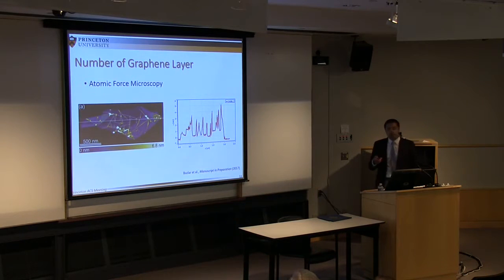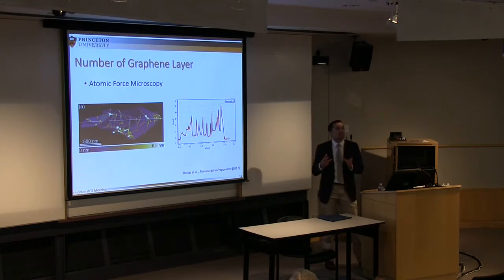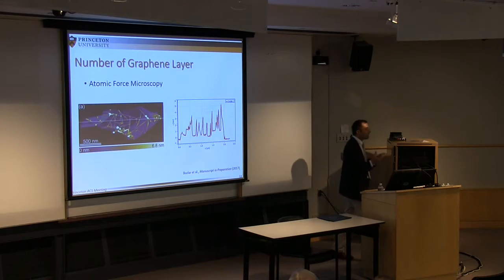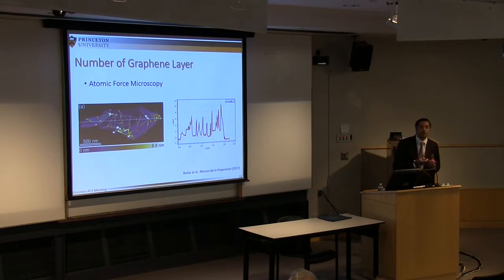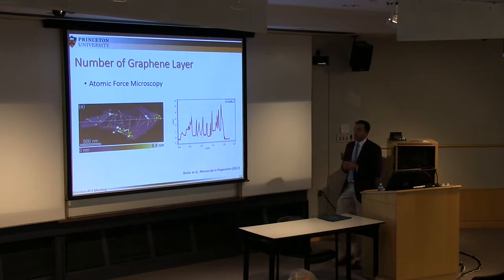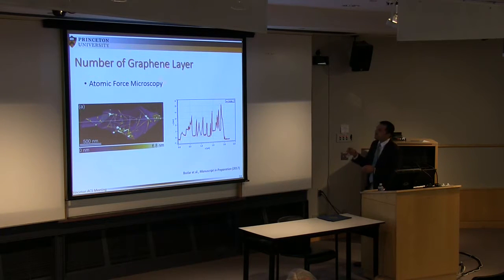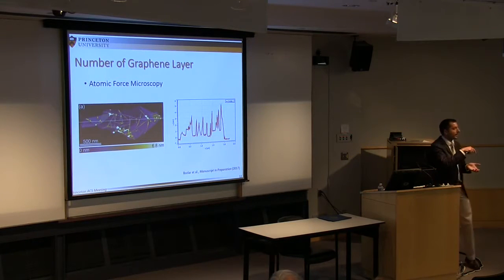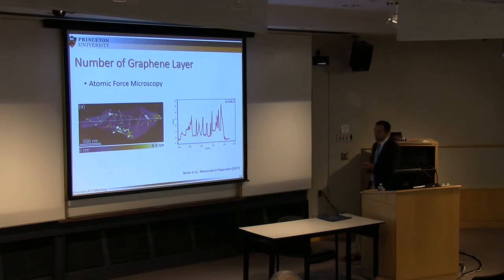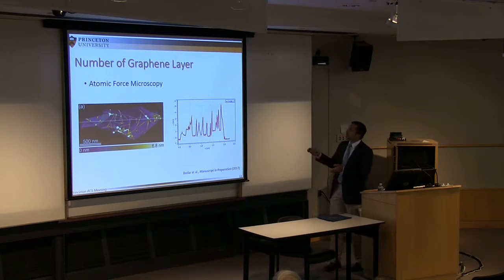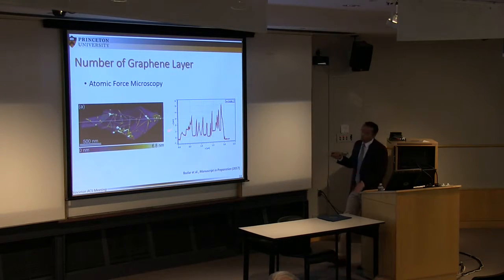Another way of characterizing the material, so what's important here is to make sure and convincingly prove that we have a single layer. Another way, but a slower way, is the use of atomic force microscopy. The idea is to come with a very sharp and hard tip and scan a surface and resolve the imaging from the height profile. So this is a functionalized graphene that was made in our lab.